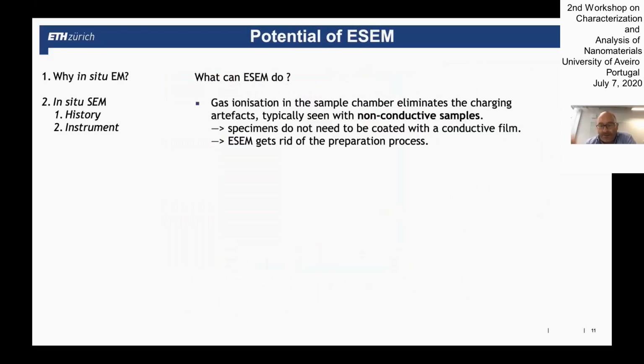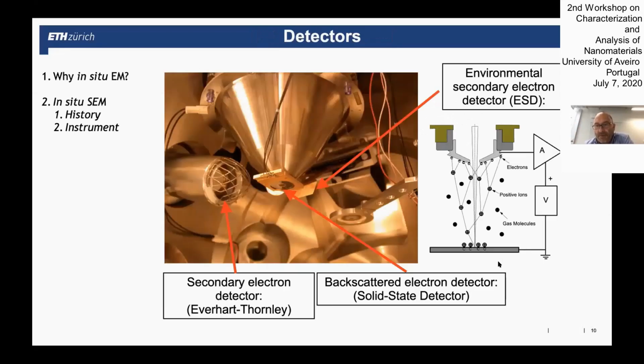The good thing is, and I should maybe go back to this slide, I'm sorry for that. Because when the electron beam hits the sample, you will get secondary electrons that are getting emitted. And it's often happening when you look at samples that are non-conducting, that they can charge up in the SEM. So for many investigations in SEM, you have actually to coat your non-conductive samples either with a film of carbon or you deposit some metal on top to make them conductive.